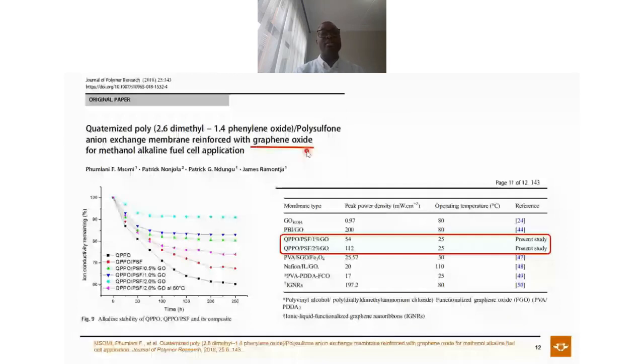We also looked at the same membrane, but this time around we added graphene oxide. We wanted to see what a carbon-based material would do in this membrane. Remember, we spoke about the degradation of the membrane. We studied the degradation of the membrane. Interestingly, when we add graphene oxide, there was less degradation after 250 hours. If you look at this material, this color, you can see that after 250 hours, there was actually less than 10% degradation. We started at 100%. After 250 hours, we were still above 90%. That tells us this membrane is able to perform at its highest level. So if you look at this graph, all of the membranes which had graphene oxide were able to retain more than 70% of their conductive sites.